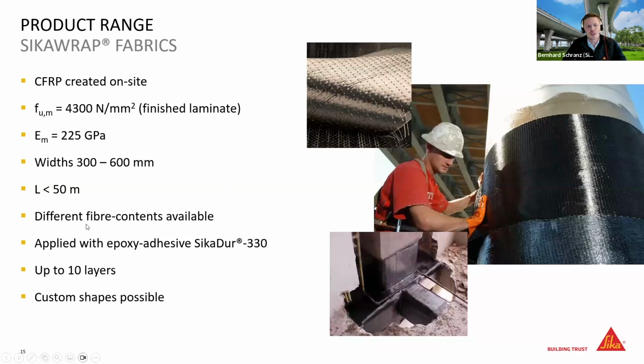We also have different fiber contents depending on the structural needs and on the loading. This is the epoxy that you need with this material. It's a little bit less filled, or higher viscosity, so it nicely penetrates through the mesh here. Up to 10 layers, depending on the structural application, can be used. And of course, as you see here also, custom shapes are possible.